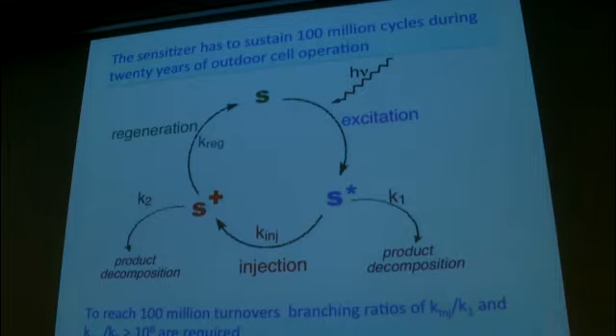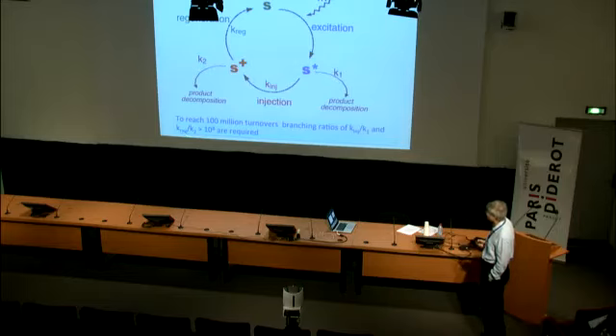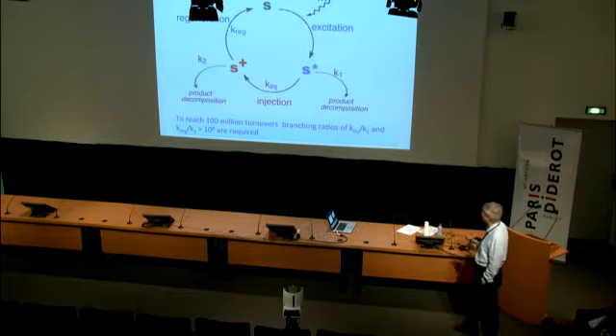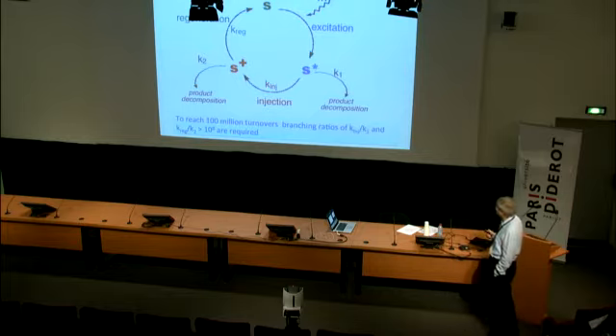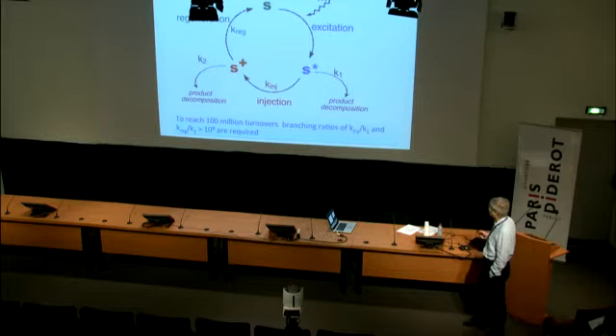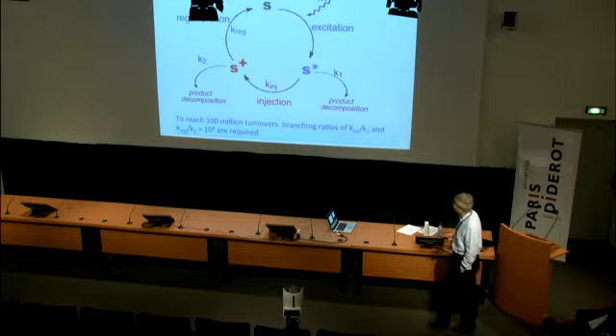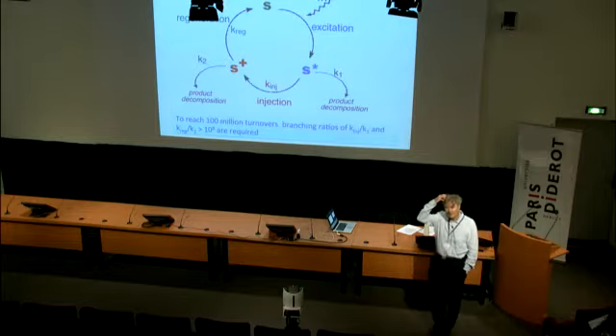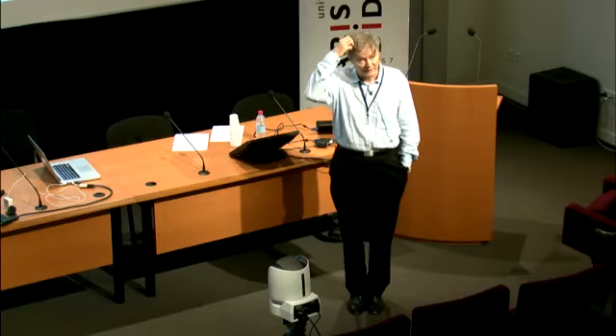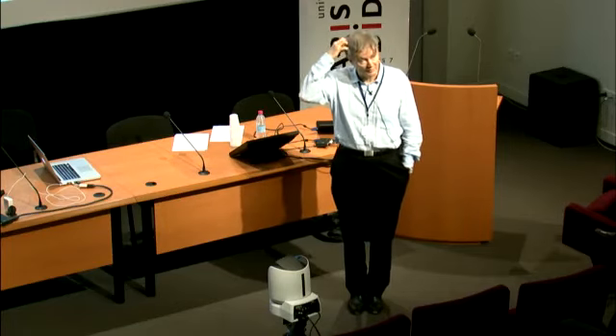100 million cycles have to be sustained over 20 years. And I have written a paper in Comptes Rendus some time ago where I went through those requirements. A simple branching ratio requirement. You have to have 10 to the 8 times faster injection than any bleeding channel from the excited state. And the same thing here from the oxidized state of the dye. This can be checked. You don't have to wait 20 years every time.